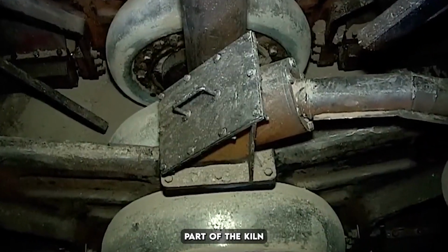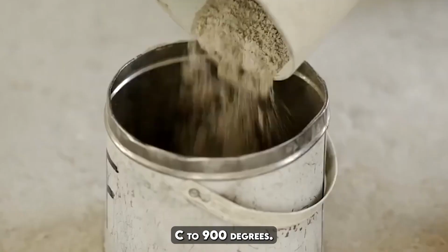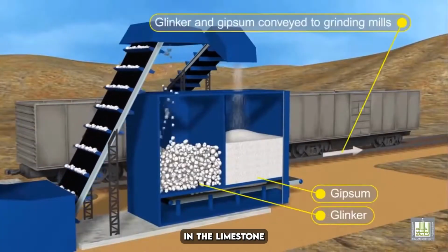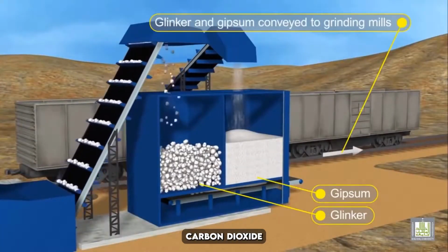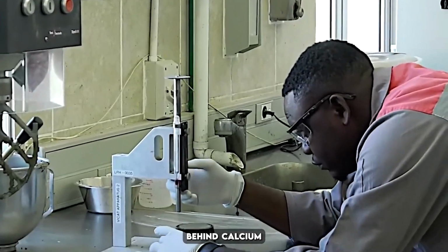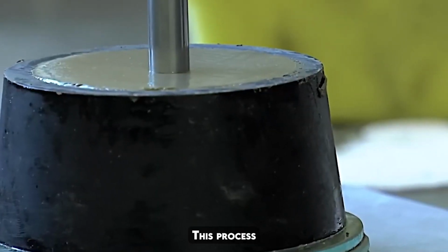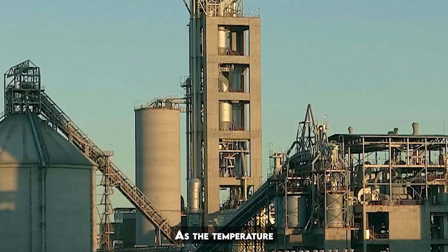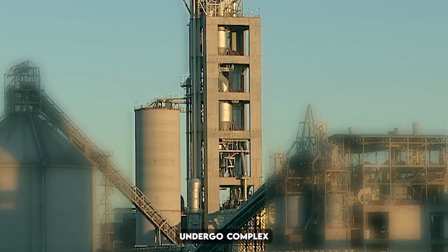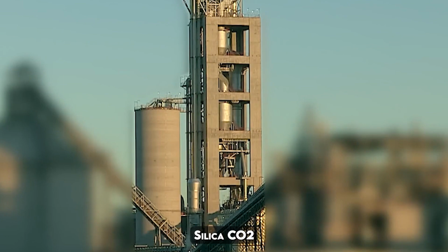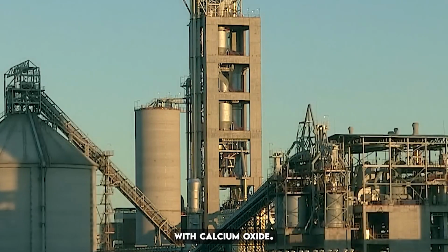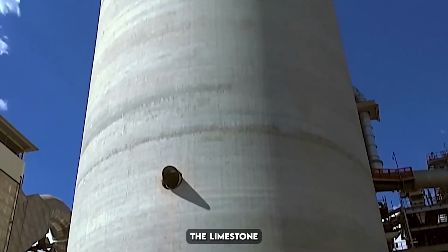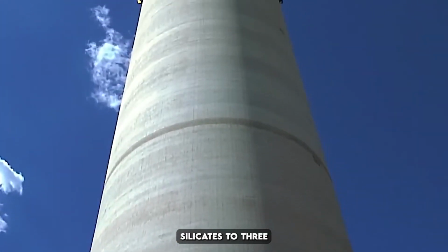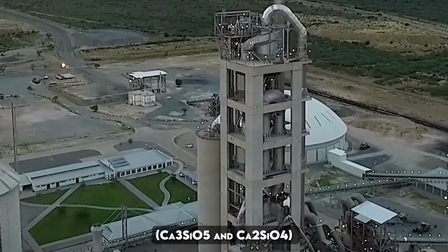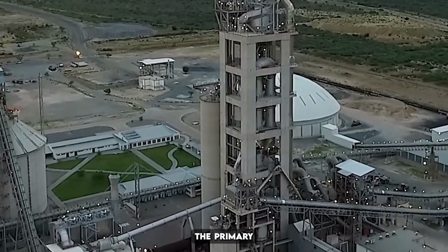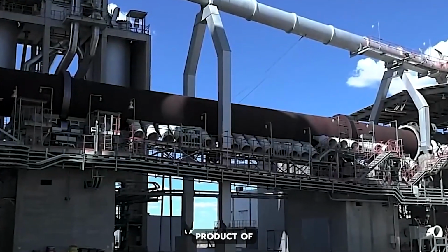In the lower part of the kiln, at temperatures around 700 degrees C to 900 degrees C, carbonates in the limestone decompose, releasing carbon dioxide, CO2, and leaving behind calcium oxide, CaO. This process is known as calcination. As the temperature increases further, the remaining raw materials undergo complex chemical reactions. Silica, SiO2, from the clay or shale reacts with calcium oxide, CaO, from the limestone to form calcium silicates, Ca3SiO5 and Ca2SiO4, and other compounds. These calcium silicates are the primary constituents of clinker, the intermediate product of cement production.